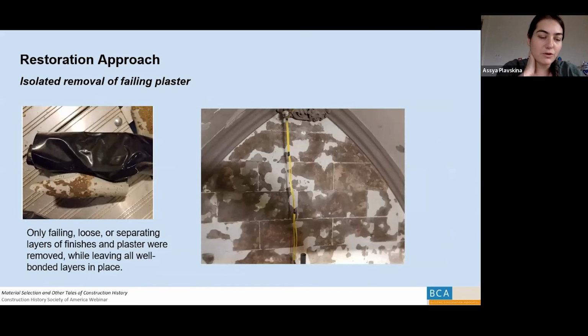You can see that in these photographs. On the left, that's a bit of rolled up duct tape with some of the failed finish layers attached to it. There on the wall, you see some removed finish layers, that's failed paint, overpaint, and that's exposed that sort of original finish. And towards the left of the photograph, you see some islands of what appears to be plaster. That is where that failed finish coat actually came off. I know this appears a little extreme, but I do want to assure you that this really was the most conservative approach. We tried to salvage what we could, but all of the layers that were removed were layers that were already in the process of coming off anyway. And so we just basically sped that up a little bit.